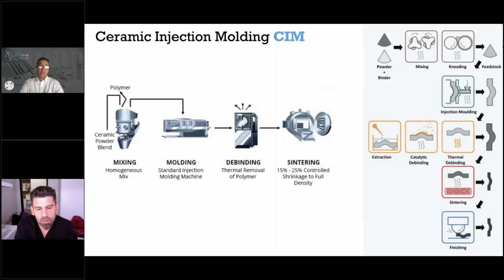The process, the simplified way, is that you have a powder, the zirconia powder. This comes in a grain, and then you have an organic binder. This is mixed and kneaded together. You obtain what's called the feedstock. That's the raw material. Once you have the powder and the binder together, that's called the feedstock.